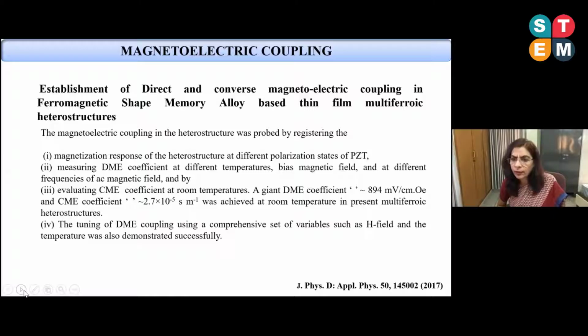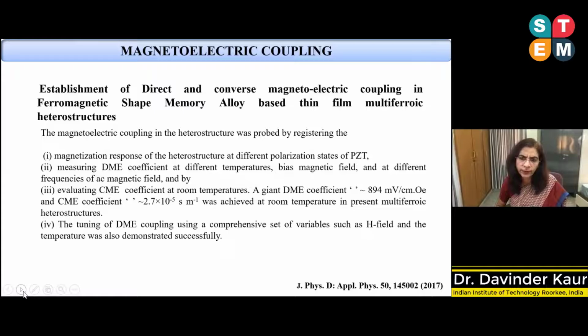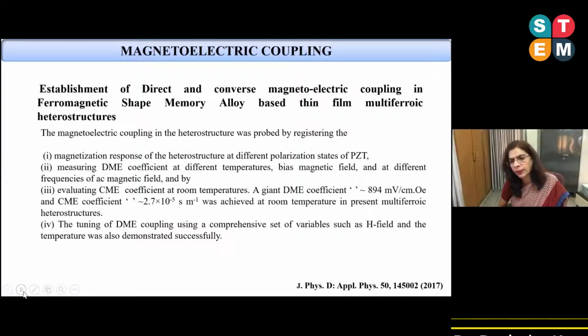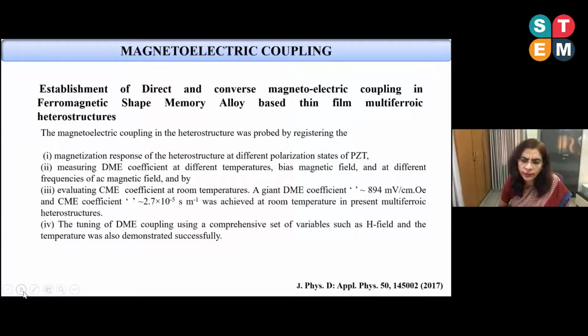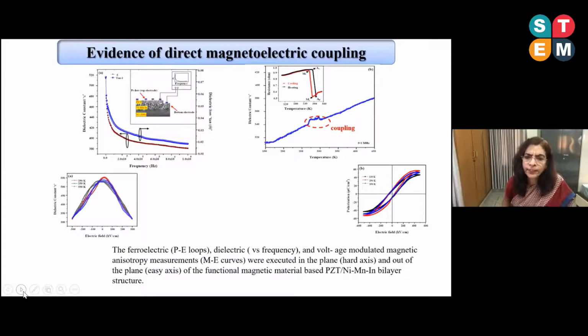The value of the direct magnetoelectric coefficient was observed to be 894 millivolt per centimeter Ørsted, and the converse magnetoelectric coefficient was found to be 2.7 into 10 to the power minus 5 seconds per meter at room temperature. Then the tuning of the DME coupling using a comprehensive set of variables such as magnetic field and temperature was also demonstrated successfully.